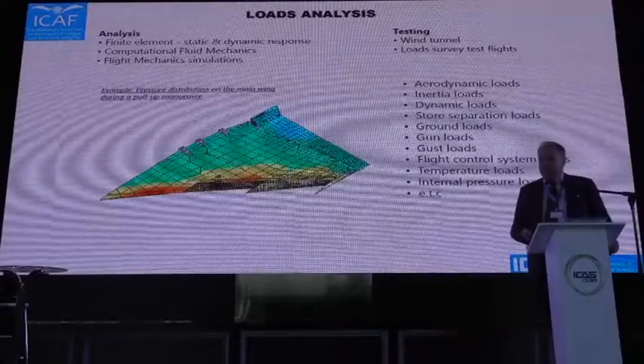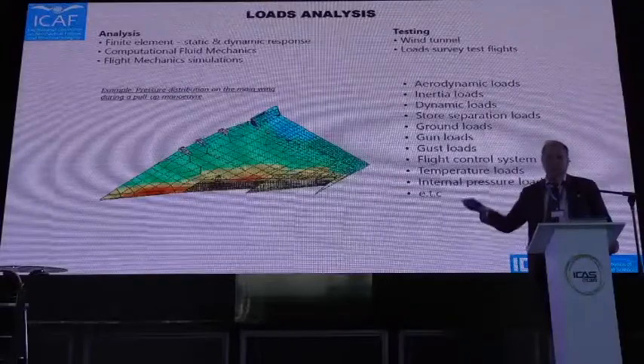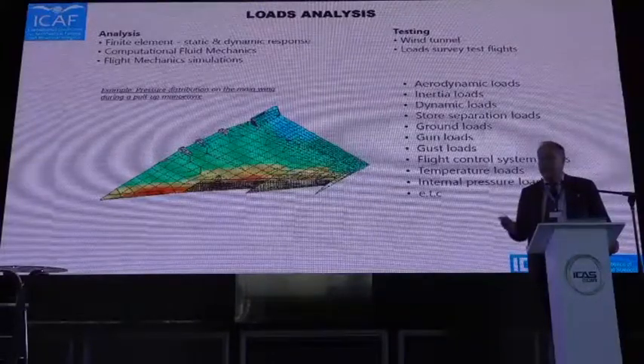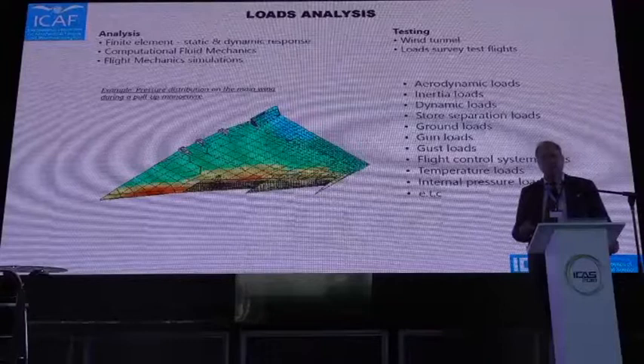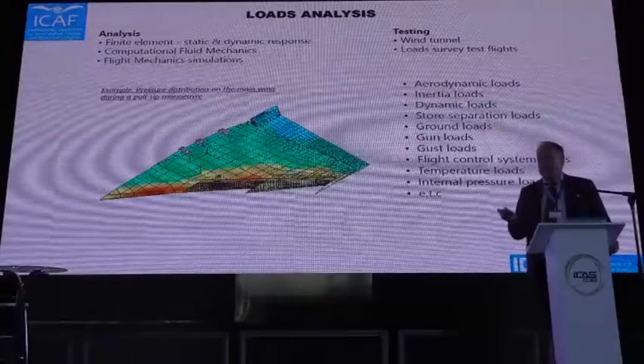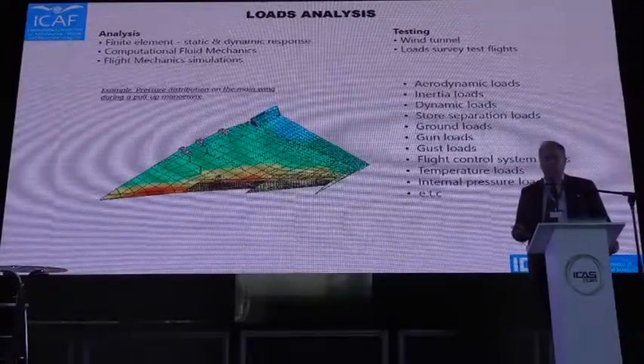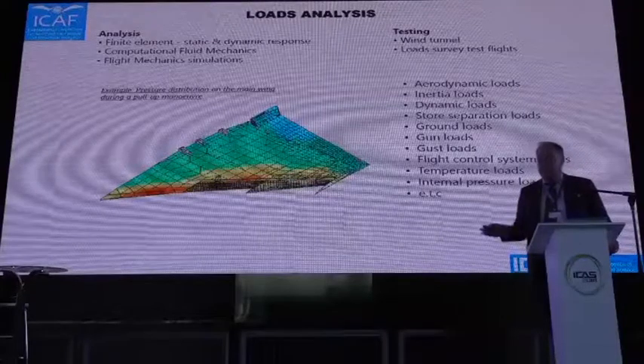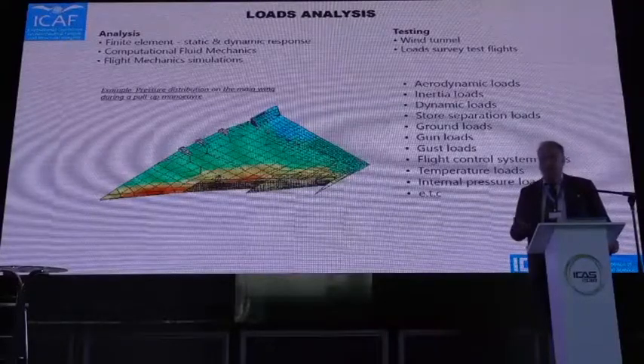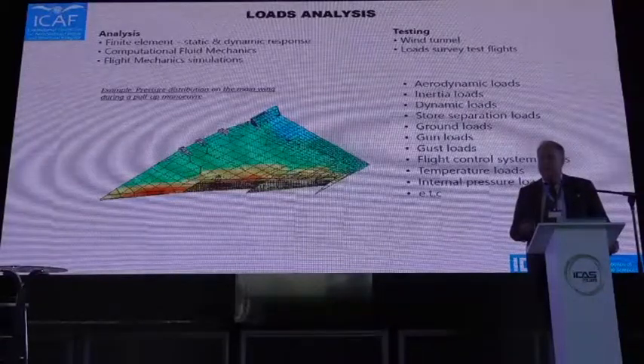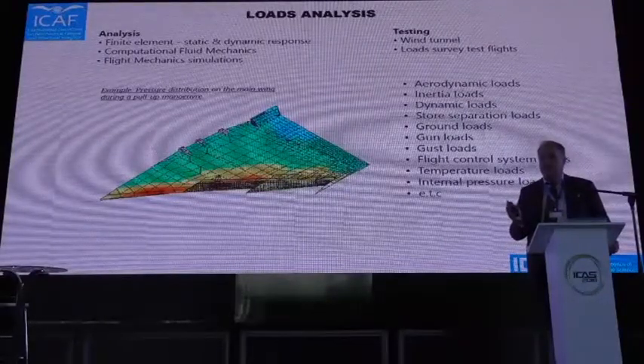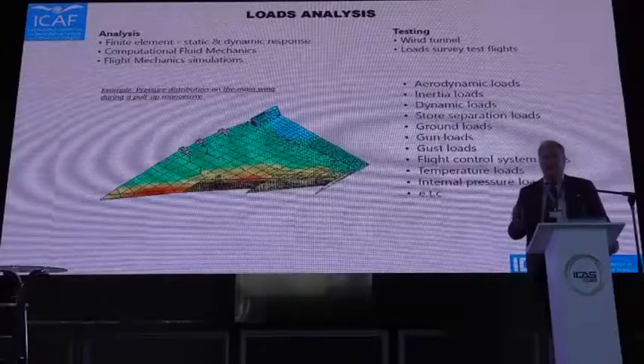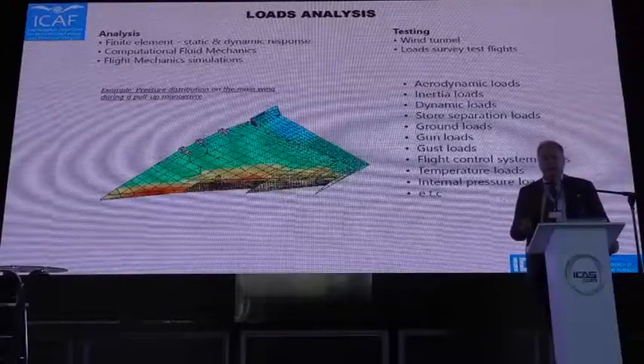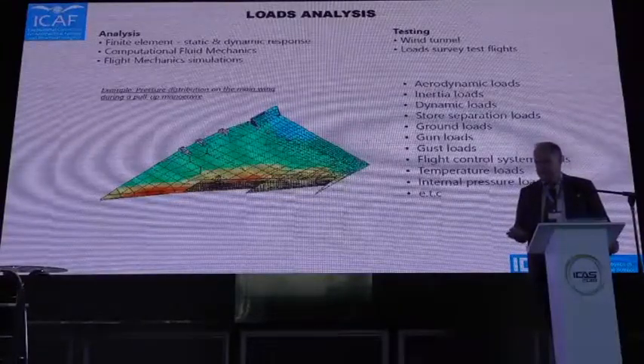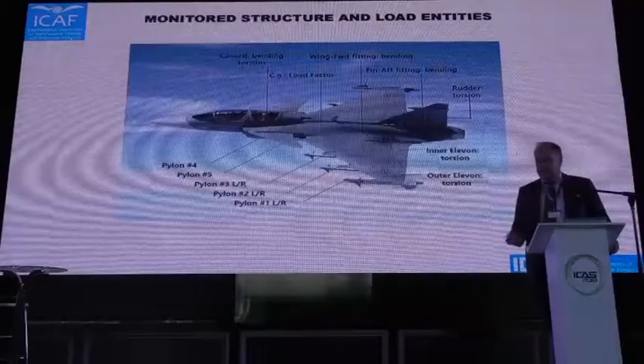When it comes to civil aircraft, the ground-air-ground cycle is very dominant, and we typically design for 60 to 100,000 flight hours or so. For fighter aircraft, the maneuver loads typically dominate the fatigue life, and therefore we have much larger stresses, and lives are in the order of 1/10 of civil aircraft, 6 to 10,000 flight hours or so. I guess I don't need to go through.